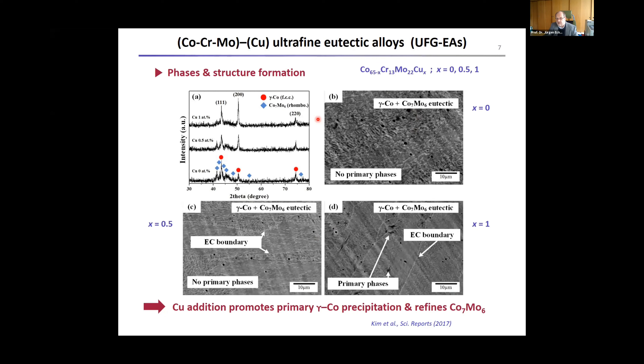This can be triggered by adding a little more copper. Copper acts as a nucleant for these phases and more or less promotes the primary precipitation of gamma-cobalt and refines the intermetallic phases. So you can again play, when you adjust and fine-tune the composition, with the solidification microstructure you may get for a given processing condition.